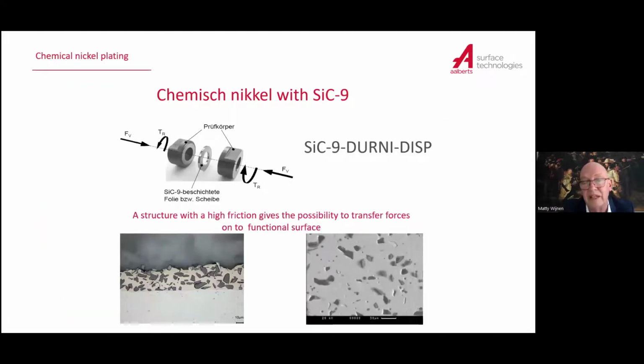And you can put in a bigger part of silicon carbide, and that's a special coating which we do in Eindhoven and which is used for friction transfer. That means if I plate a part with this coating, silicon carbide particles will stick out of the coating. It increases your roughness, of course, so it doesn't lower your coefficient of friction, but it raises your coefficient of friction. But it has another advantage: when I put another part against that, the silicon carbide particles will be pressed into the material and will make a vast connection with each other so that no movement is possible anymore. That's something which is very valuable for some applications.